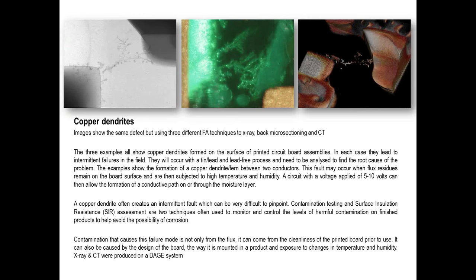What I'm showing you here is dendrites. And dendrites can be detected using x-ray or CT or optically. This is one particular board that I was doing failure analysis on. I thought it would be neat to show it with x-ray, which we did on the left-hand side, and on the right, with the assistance of Dave Bernard, you can see the dendrite formation on my sample on the right-hand side.